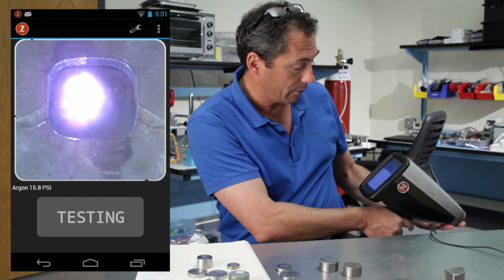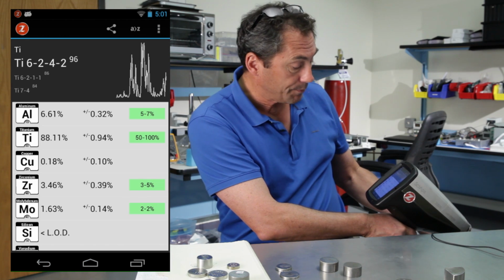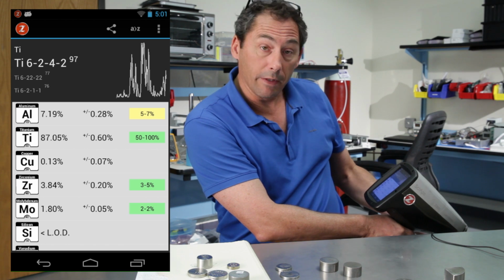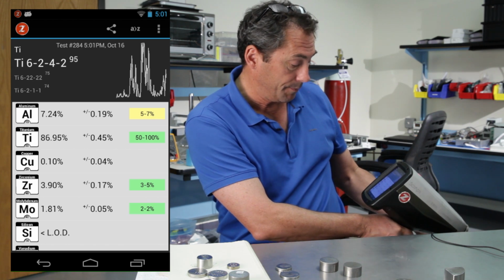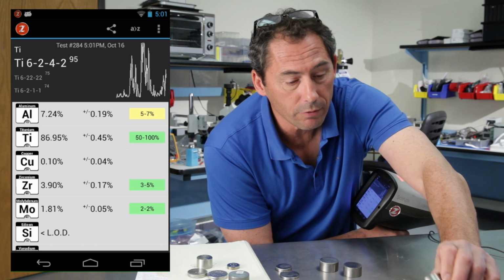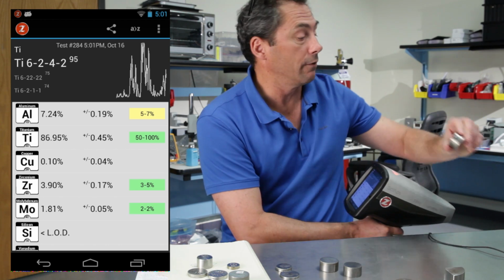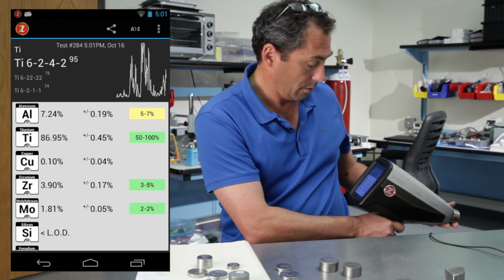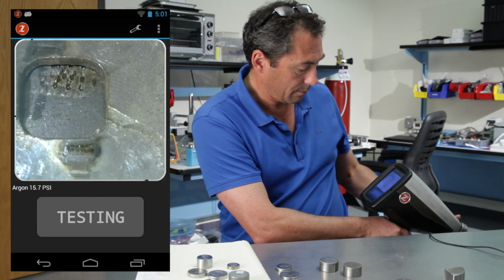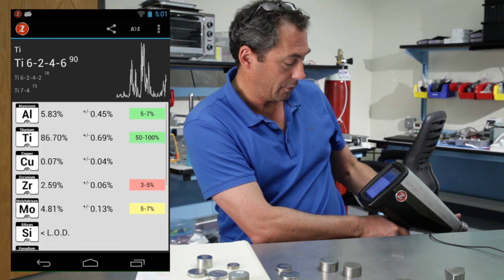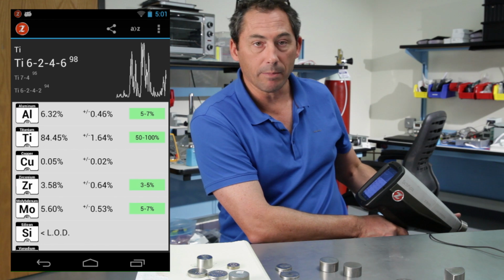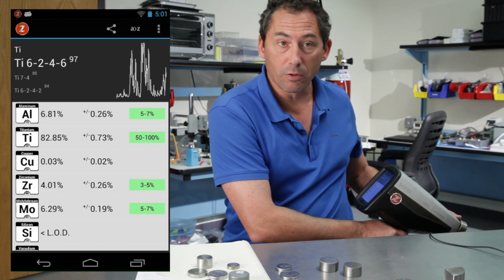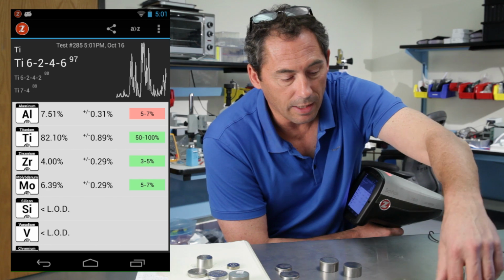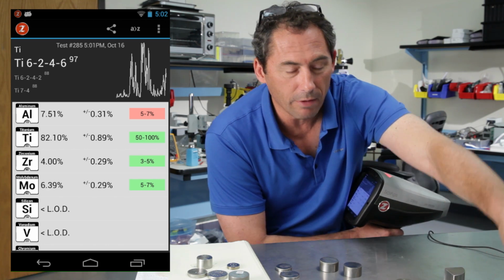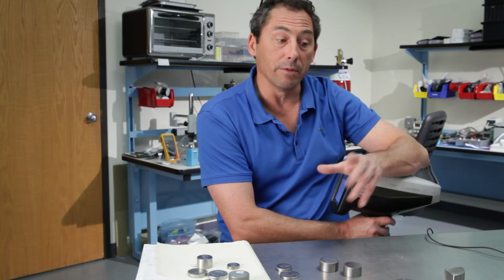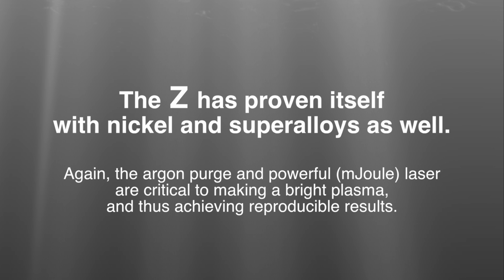This is a 6242 as it comes up. So you see the moly is about 1.8%. Now let's shoot our 6246. Measure 6246, again up around 6% moly. So that's a very, very fast, quick separation on two alloys that have historically been hard to separate with some of the optical emission techniques that are used in the industry.